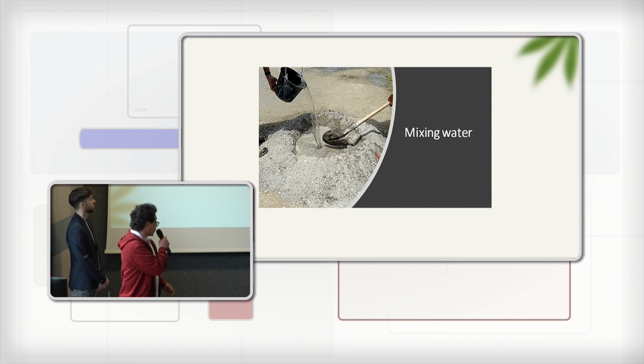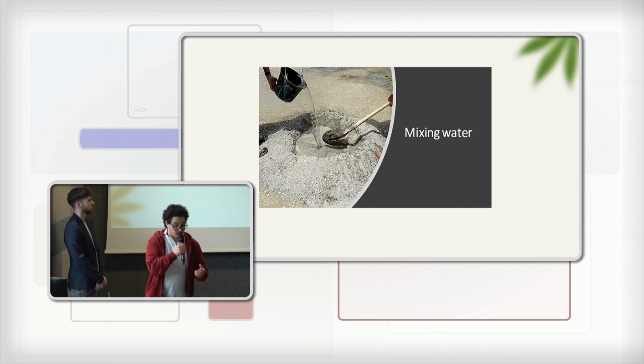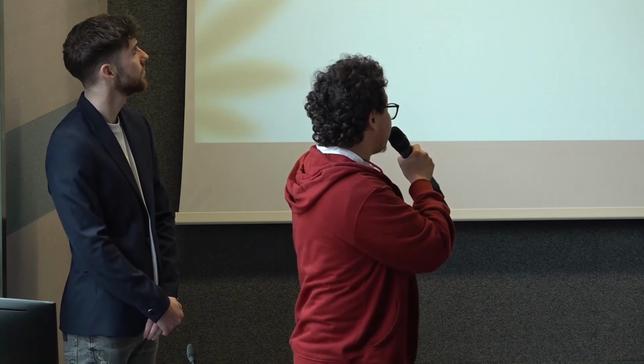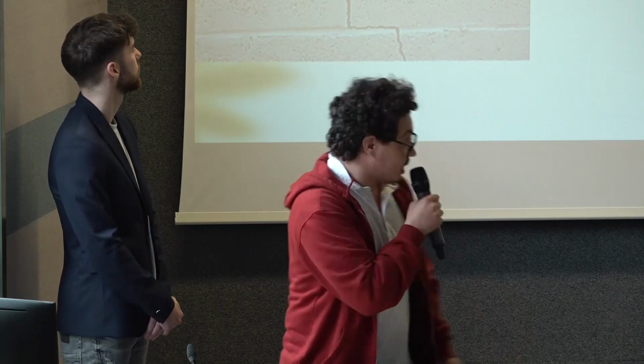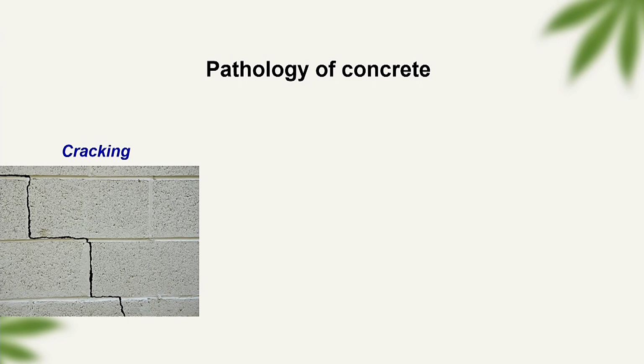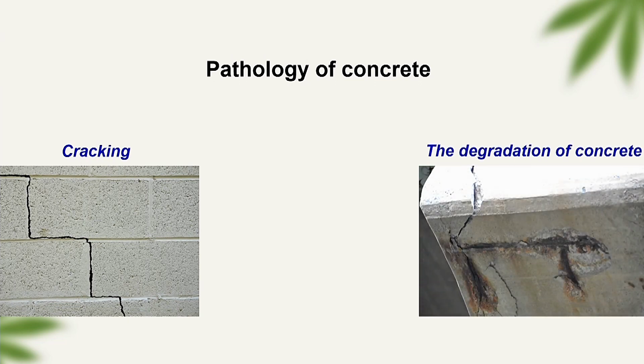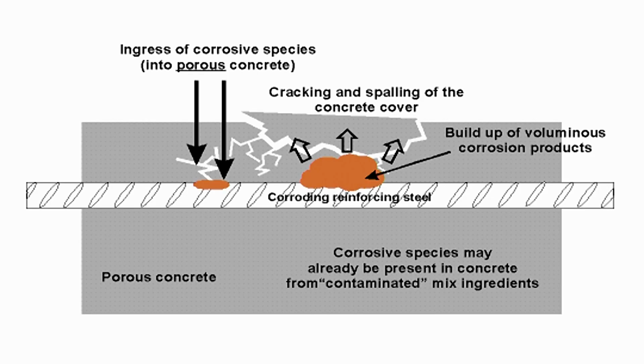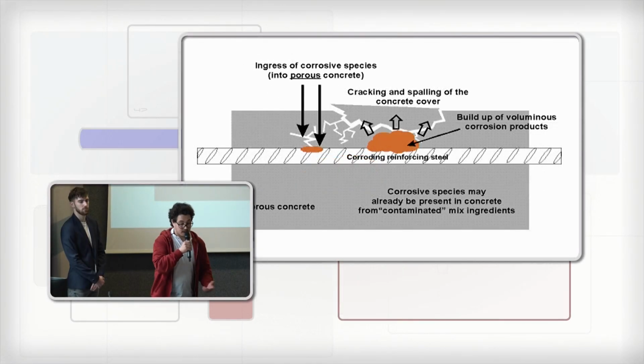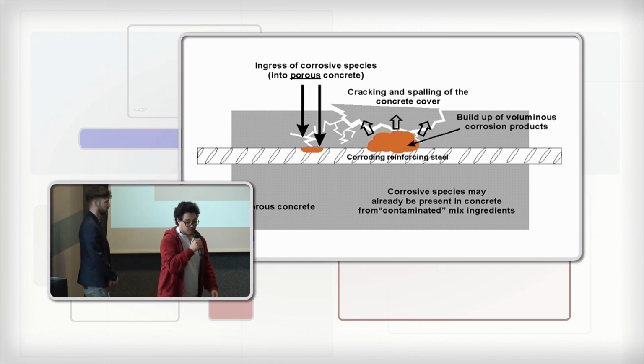And the other main component is water, because we need to use water not more and not less to have good properties of concrete. But concrete has many problems. For example, the pathology of concrete: we can have cracking because we use too little water or too much water. Also, the best known pathology is the degradation of concrete because of corrosion of the steel matrix. This is the mechanism of this degradation. The water comes through the pores to the matrix. Then the products of corrosion push up the concrete, so we break our concrete. My friend Karim will talk about the properties.